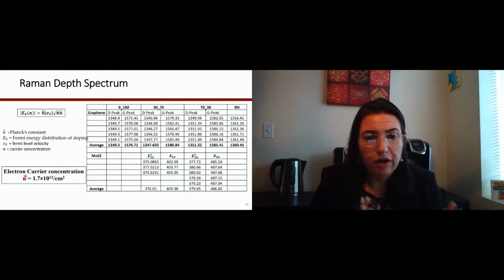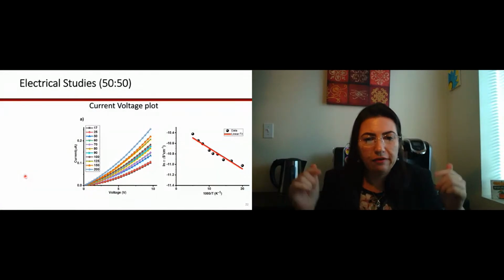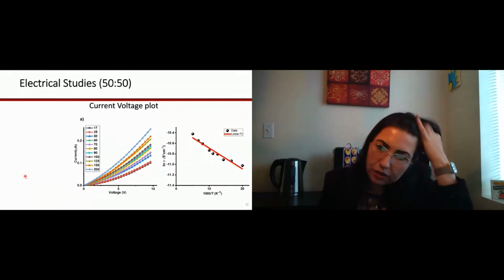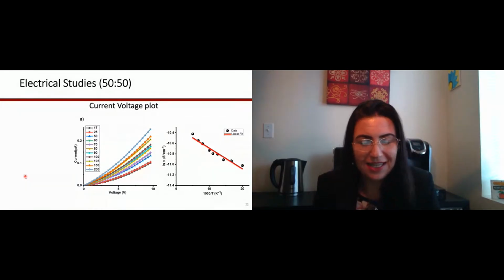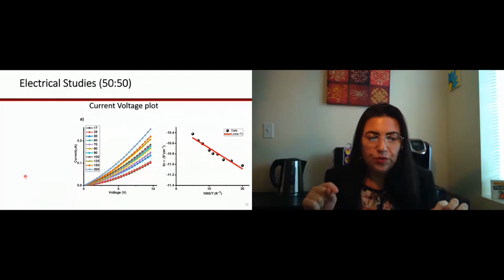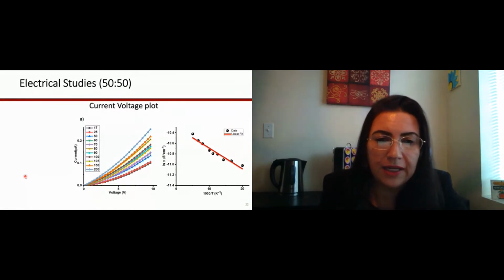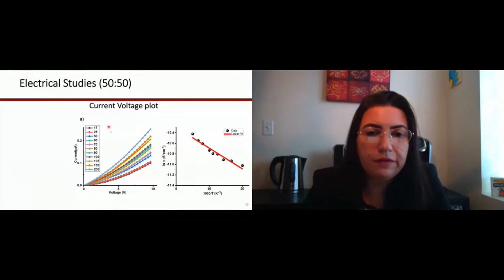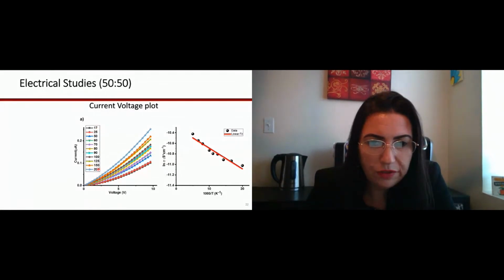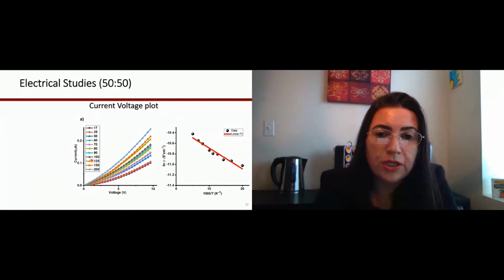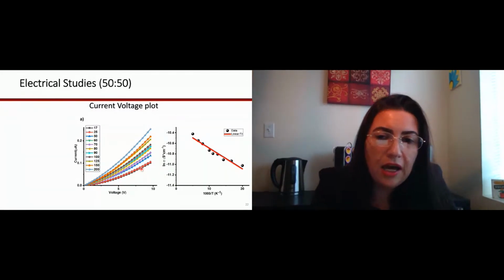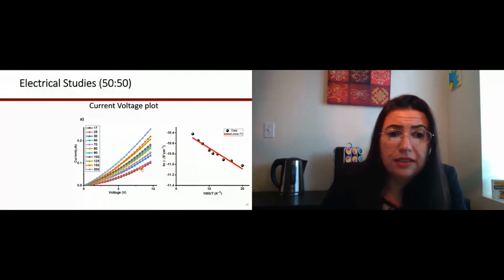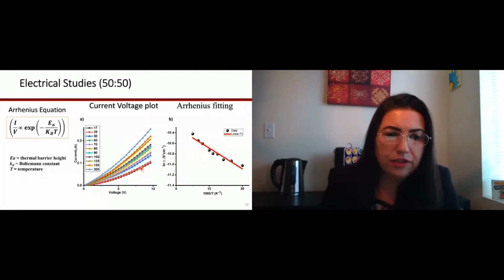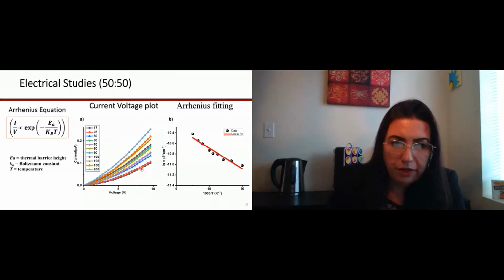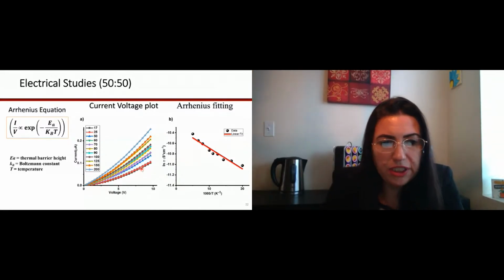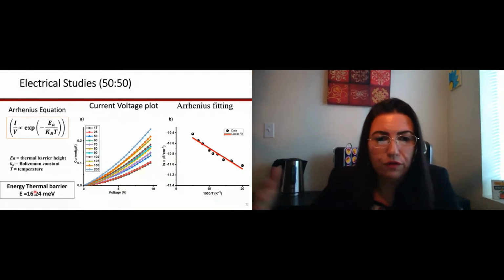So we go a little bit farther and we use a cryostat, and we have the electrodes connecting the two ends of an electronic device. And once we connect those two ends of it, we measure the current voltage going from 17 Kelvin to 200 Kelvin. Sorry, I should have a unit here for the temperature. So this is varying temperature, and using the heat, we can determine the thermal energy barrier.